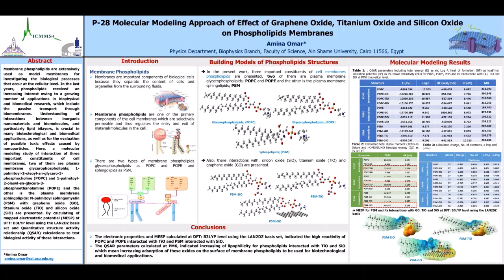The calculated electronic properties and mapping electrostatic potential indicate the high reactivity of phosphocholine POPC and phosphoethanolamine POPE interacted with the titanium oxide, and sphingomyelin PSM interacted with silicon oxide. And the result of the QSAR parameters calculated at PM6 indicates increasing lipophilicity for the phospholipids interacted with the titanium oxide and silicon oxide, which means increasing absorption of these oxides on the surface of the membrane phospholipids to be used for different biotechnological and biomedical applications.